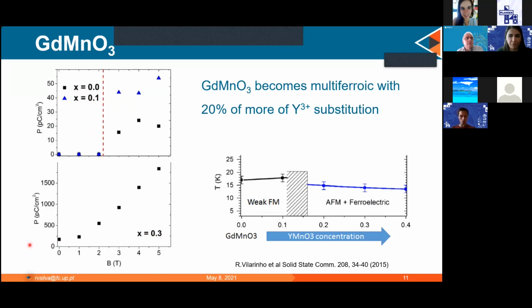So you use the atomic substitution. So now you don't have to apply a magnetic field. And then if you apply a magnetic field, the polarization actually increases and you have a large positive magnetoelectric coupling. So it's a magnetoelectric multiferroic material, let's say made by design. And this is just its phase diagram, where here you have a ferromagnetic phase, and then you have an antiferromagnetic phase, which is ferroelectric.